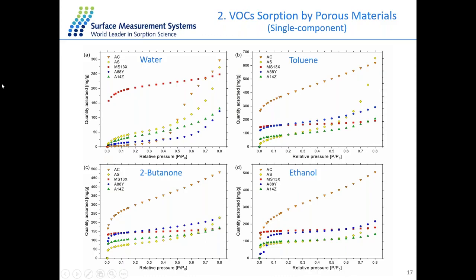For example, for the water isotherm, the spot on the top here, the red one, represents the molecular sieve, the 13X sample. 1 gram of the 13X sample will pick up around 250 milligram of moisture at 80% partial pressure. So the moisture capacity for this 13X sample is about 25%. That means the 13X sample has a very great affinity with water molecules. Even at very low partial pressure, it still can pick up lots of moisture, compared to the other porous materials, which only start picking up a significant amount of moisture at a higher humidity range. So in this case, the 13X sample seems a better choice for absorbing water.